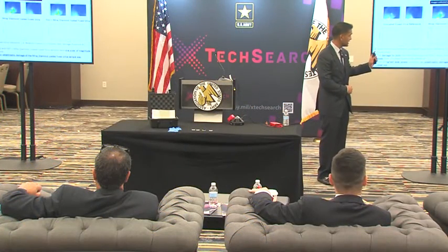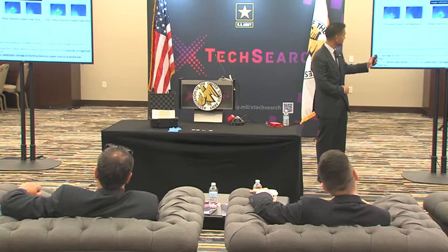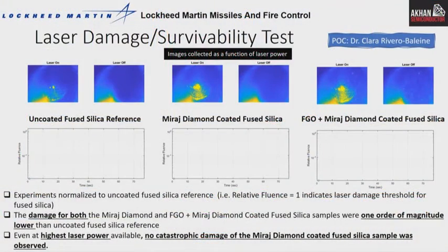Two questions. Time of the laser left on the sample. Like you said, it just dispersed the heat. So how long are we leaving that laser on the sample where it's not damaging it? So in this particular sample, they left it until damage was onset, which I believe occurred roughly at the 60-second mark. The total time duration, though, was 70 seconds for each sample in this particular test.